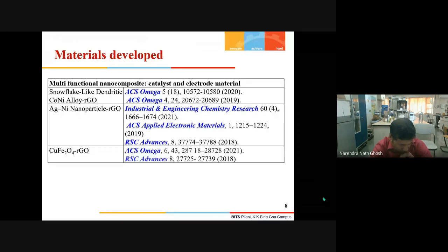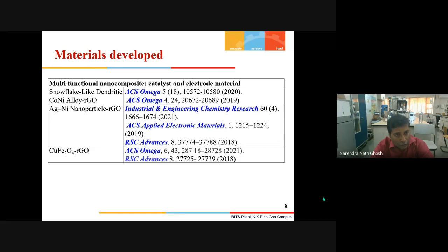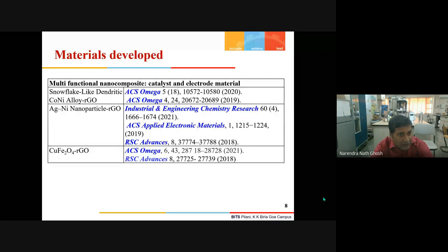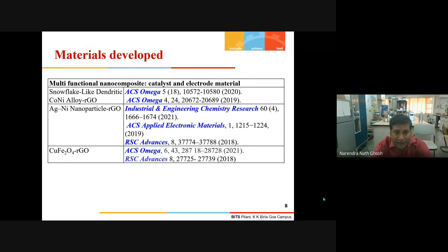Now, we have utilized some nanocomposites as multifunctional nanocomposites, which showed catalytic activity as well as activity as an electrode material. We have synthesized a cobalt nickel alloy system, which looks like a snowflake-like dendritic structure, and we have anchored it on the surface of reduced graphene oxide. Similarly, silver nickel bimetallic nanoparticles on the surface of RGO, and copper ferrite nanoparticles on the surface of RGO. These materials showed their activity both as a catalyst as well as an electrode material.